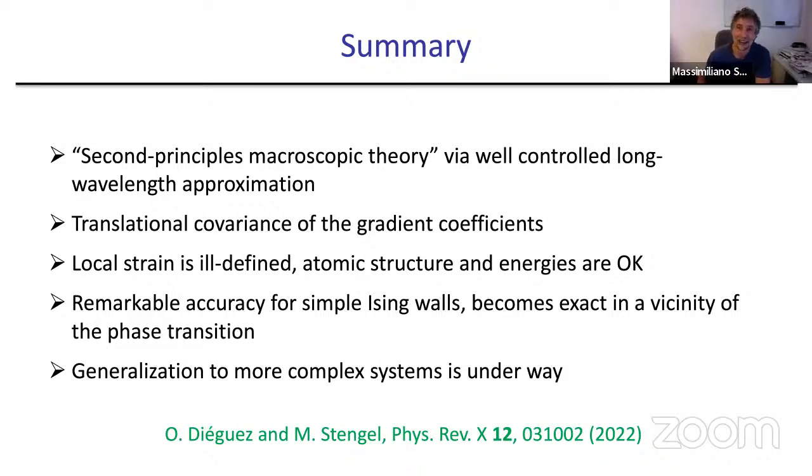Yeah, this is the thing. In order to fix the center of mass, you need to define the center of mass, and to define the center of mass, you need to put some weights on the different sublattices. These weights can be just the average of all, so you can define the average position of all atoms by choosing these weights equal for every atom, or you can look at the physical center of mass, or you can just say, okay, all the mass is contained in barium and all the rest is irrelevant.